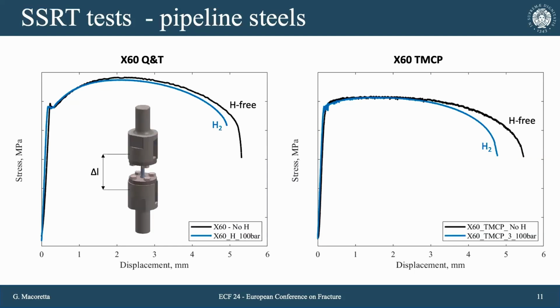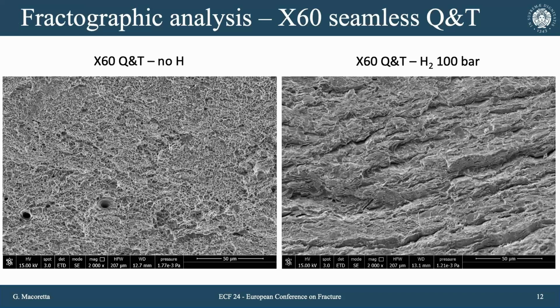If we go to the fracture surface to analyze the effect of hydrogen on the material, we can see that the hydrogen-free material presents a standard ductile surface with standard microvoid coalescence, typical of a ductile material. While when we introduce hydrogen, at least in the first half of the specimen, starting from the hole of the specimen, we can see a transgranular fracture, and so the comparison between the two surfaces is very evident, the effect of hydrogen on this material.